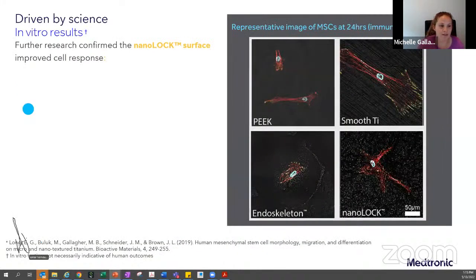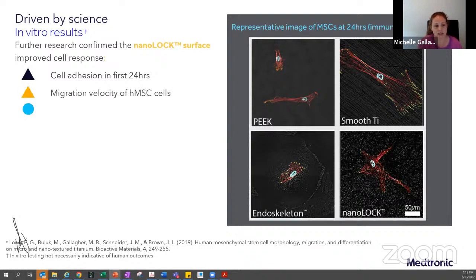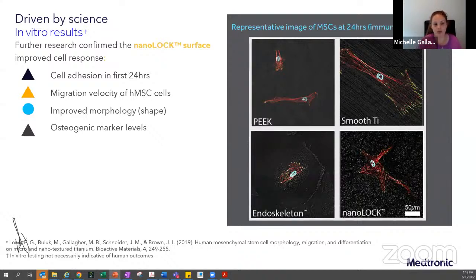And then next, we've done some further research to confirm NanoLock improves cell response. I'll go through this quickly. We looked at cell adhesion and it improved in the first 24 hours with NanoLock compared to PEEK, smooth titanium, and the endoskeleton reference surface. We had higher migration velocity, so the cells moved over the surface at a faster rate. We had improved morphology, which is a fancy word for shape. If you look to the right are the different shapes of the cells.